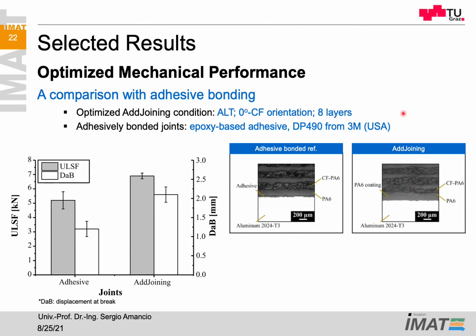Okay, these are the summarized results, where we have the ultimate lap shear force in gray, and in white the displacement at break, showing the ductility or the fracture toughness of the joint. What you can see, first of all, if we concentrate on the ultimate lap shear force, is an increase of 35.3% in ultimate lap shear force, and an increase of 75% in the displacement at break, showing an improvement of mechanical resistance and ductility of the AddJoints in comparison to the adhesive bonded joints.